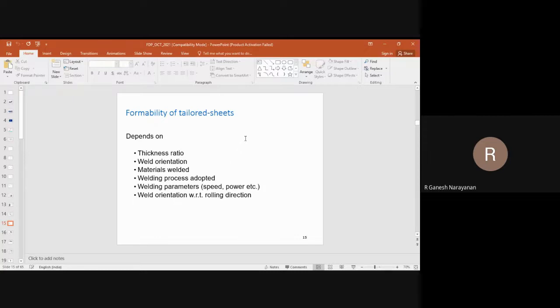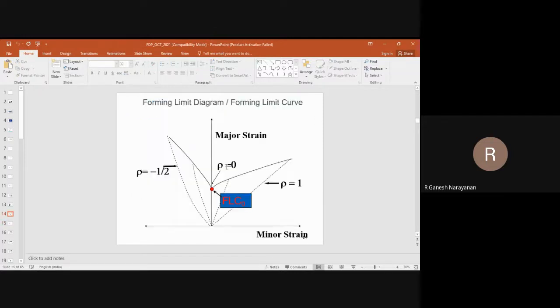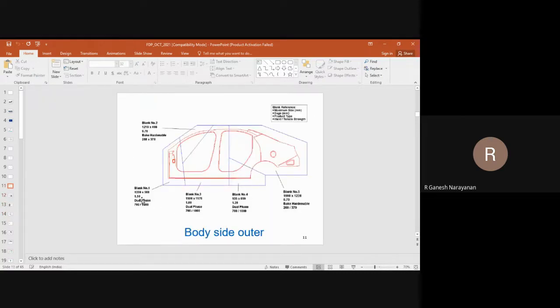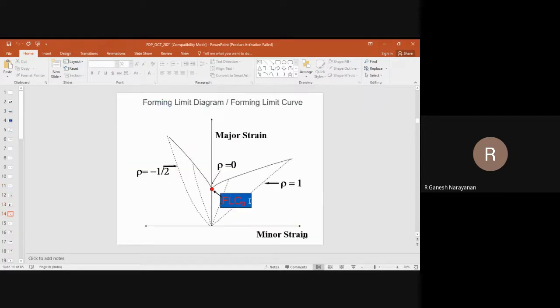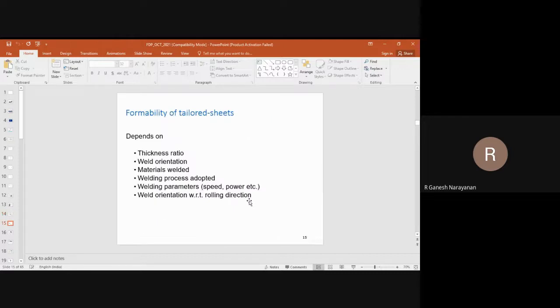Other than those properties of one sheet, when you weld two sheets to make these tailor-made sheets, some additional parameters and properties come into the picture. That is what I have listed here. Thickness ratio: I already gave you several examples before. Thickness ratio means thinner sheet thickness to thicker sheet thickness. For example, here if you see 1.5 to 1.8, and then 1.2 to 2.7. If you take these two sheets, left and right, 1.5 divided by 1.8, that is the thickness ratio. Sometimes you can do vice versa also, thicker to thinner is also possible.